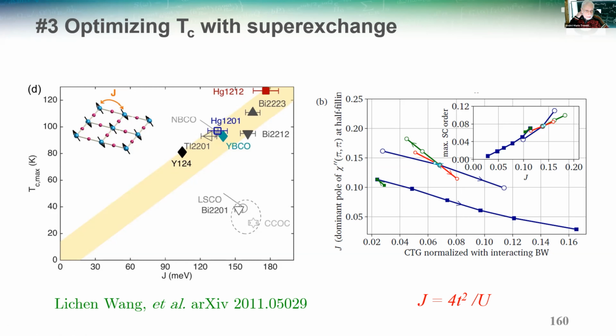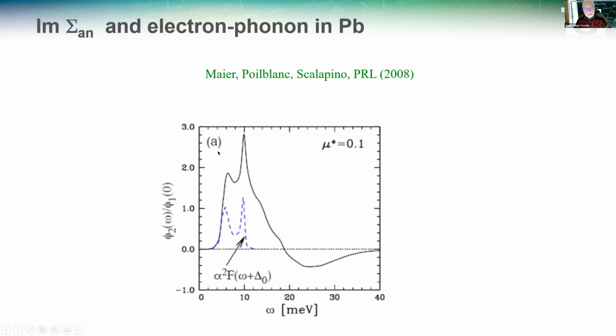Yes, okay. That's a good point, and I'm coming to this in the next slide, because indeed the mean field arguments that I showed suggest, like you just said, that TC and J should basically be the same, right? In some ways. But let's look at the glue in the weak coupling in the one band model. But before I do the one band model, let me go back even to BCS superconductivity: electron phonon superconductivity in lead. Here what is plotted is the imaginary part of the anomalous self-energy, the self-energy for the Cooper pair, as a function of frequency. And this is measured by tunneling experiment, and you see that there are two peaks.